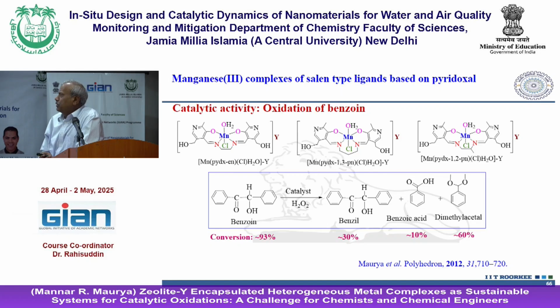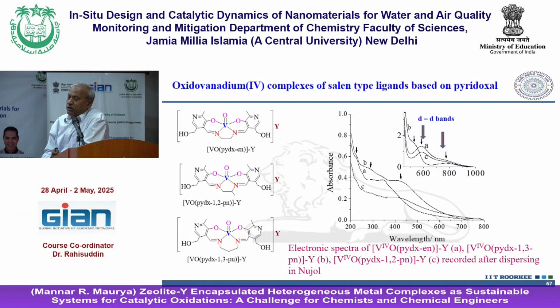All characterizations are shown here, and here you will see very clearly that even in the encapsulated recording of the electronic spectrum, all the d-d bands can be seen, though it is not much expected for the manganese compound because this is forbidden. But due to a change in symmetry, or broken symmetry, if you know the basics, you should be able to see the d-d band, and of course the charge transfer band can be seen. So it is seen here. It means the symmetry has broken down and you are getting some results. And also in the case of vanadium, it is very clear to see that.